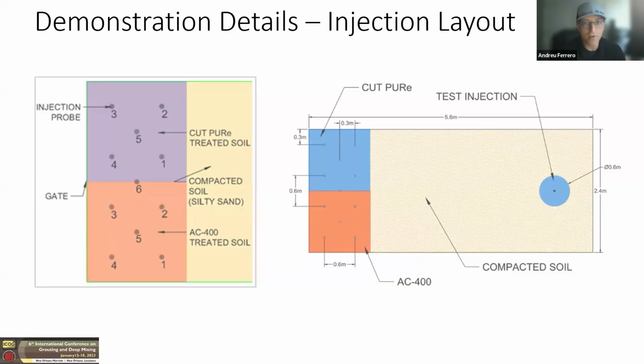So the injection layout is as shown on the screen. We did a test injection on one side of the container, and then we did a polyurethane treatment zone and an acrylate treatment zone as shown in the layout here. The gate of the container was along the treated side with the intention of showcasing the stand-up capacity of these materials.